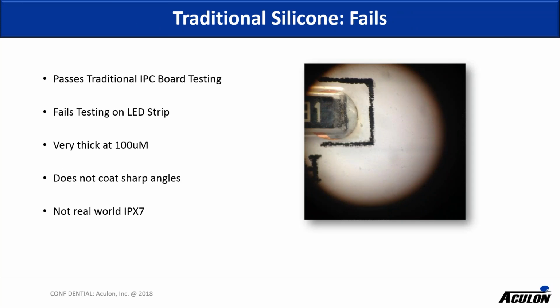Now, to get into some of the testing we ran: a common conformal silicone, which passes the traditional IPC testing with flying colors, fails on the LED strip testing in almost all cases. Even putting down multiple coats, in some areas as thick as 100 microns, the LED strip still failed. That's because they don't coat the sharp angles. They slump off the board, so you may have 100 microns of coating on top of the resistor or on the sides of the resistor, but those top corner edges are exposed, and you can see in the picture that there is significant corrosion on that top edge. That silicone does not lead to a real-world IPX7 approach.